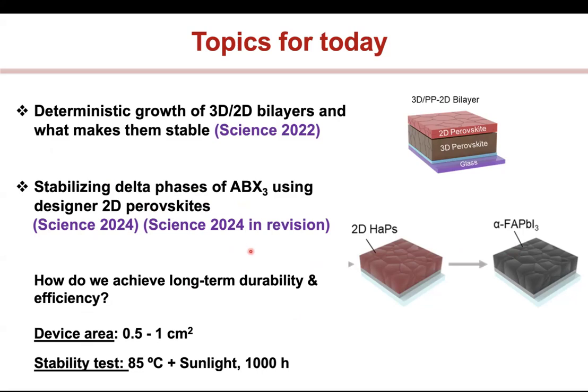And the goal that we had set ourselves was to be able to do a stability test which has never been done before, which is at 85 degrees C under one sun illumination, at maximum power point. 85 degrees C is an accelerated test, which means all the degradation processes that occur are accelerated because now the kinetics of your process are faster. And so if you can get a device to survive this test, then that can be extrapolated to really long lifetimes. When we did this, there was no solar cell which could survive this type of a test. Okay. So that's what we will be talking about.